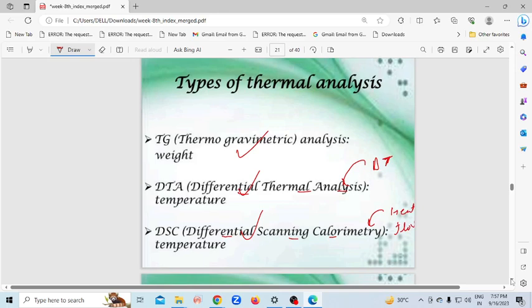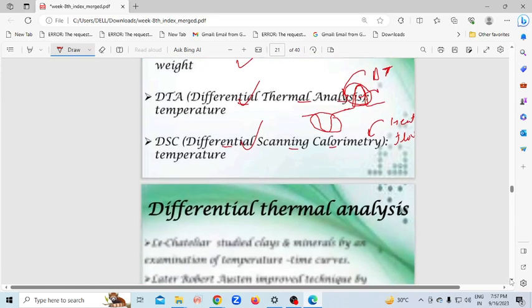Okay, so here you will get peaks. Okay, so this peak tells you how much energy your sample is taking, or in the case of an exothermic peak, how much energy your sample is releasing. Okay, so by measuring the area of this peak, you can measure heat. Okay, how much heat your sample is taking, and according to that you can quantify which sample is there and which phenomenon is occurring. Okay, what is occurring, it is crystallization, melting, glass transition, whatever. Okay, so you can correlate these things.